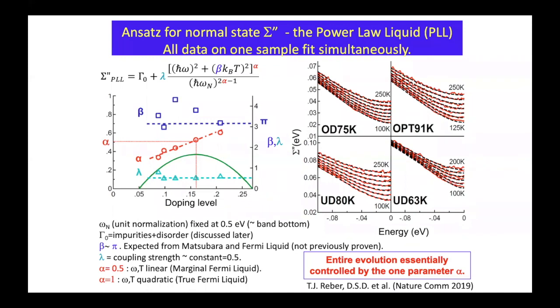First of all, this is here to make my units work. Because this is energy, h bar omega, this needs to be energy, but as this alpha varies, I need to keep this in energy units. So omega N is something we put in, and we put it in as a very large number. I think it's 0.5 eV for us, but it essentially drops out. Let's just go to the case alpha is 0.5. 2 times 0.5 is 1, minus 1 is 0, completely drops out there. It's something to keep the units right, and we've tried a variety of values. It does matter a little bit here and here, but only very weakly.